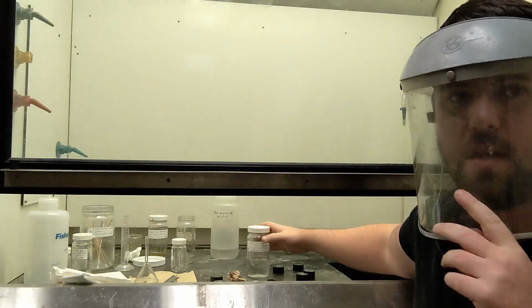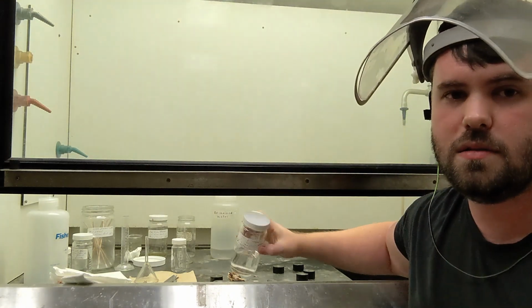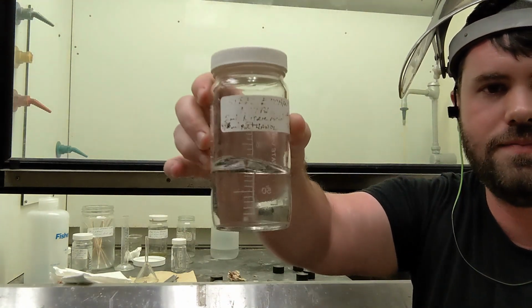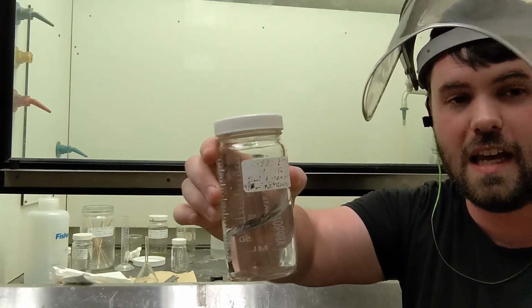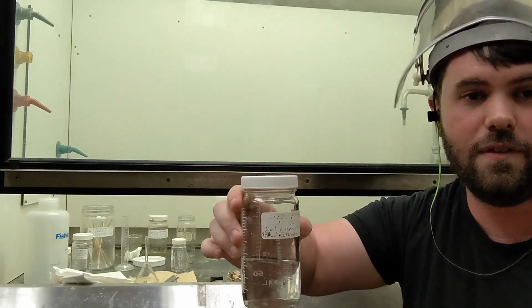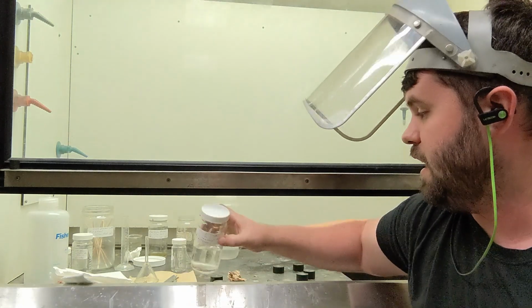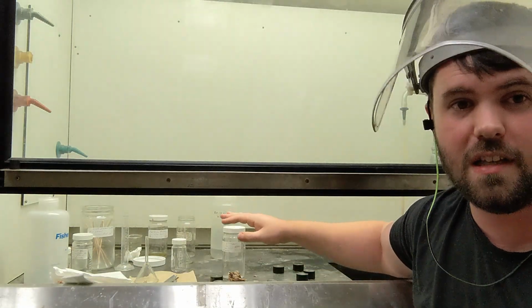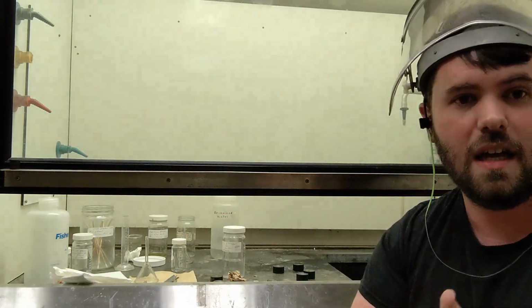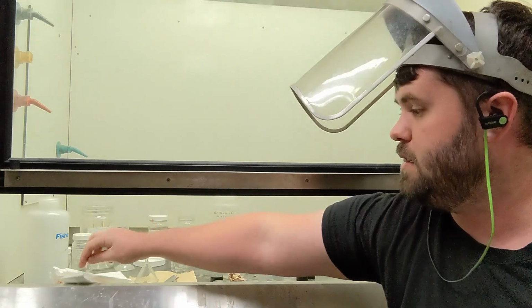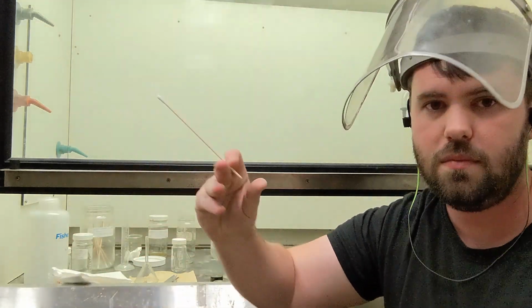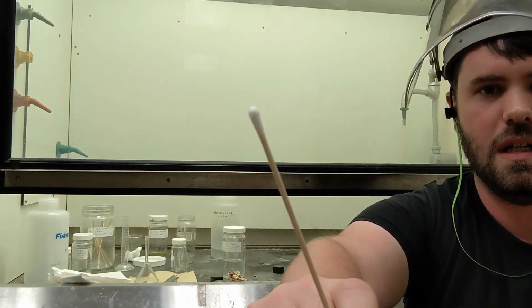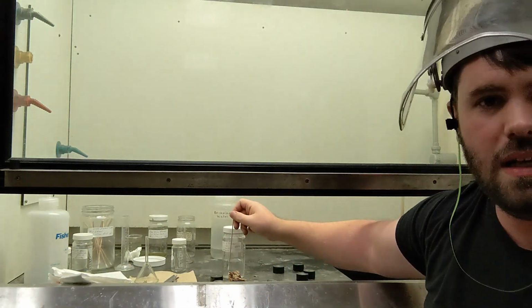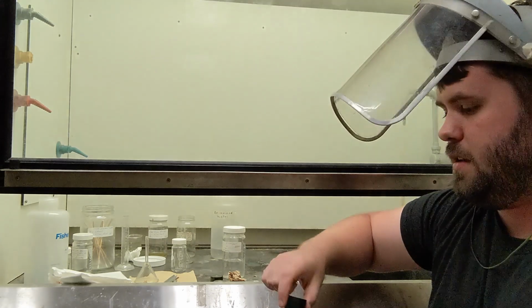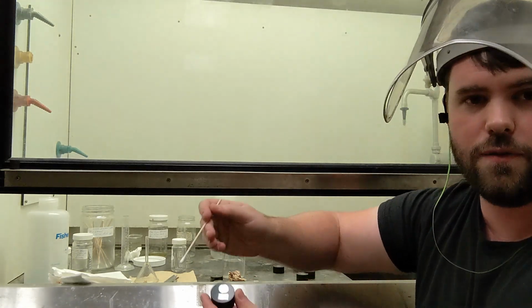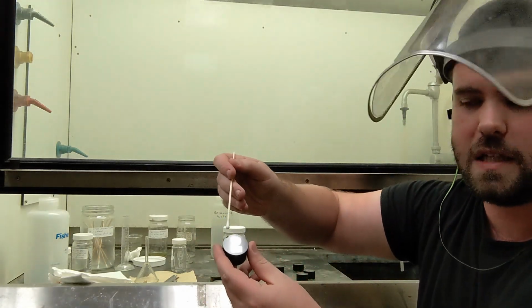So I've already prepared some Nital. It is in this bottle. It looks like water. You really can't tell the difference until you open the jug. And if you were to smell it, it smells terrible. But hopefully you don't have to, because it's inside the fume hood. To etch, it is relatively easy. You take these long Q-tips, like so. You dip it in the Nital, and then you wipe it on the surface of your sample, like so.